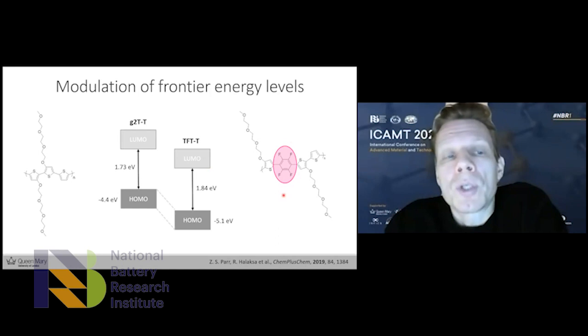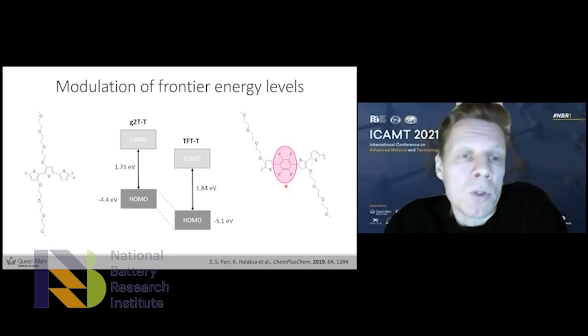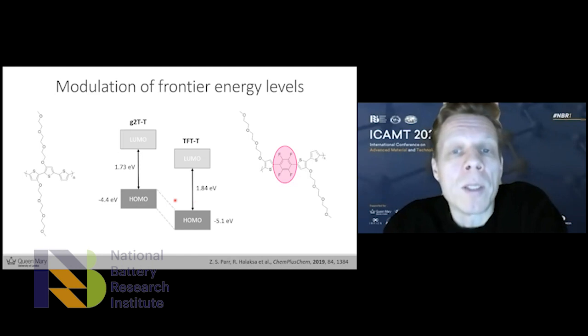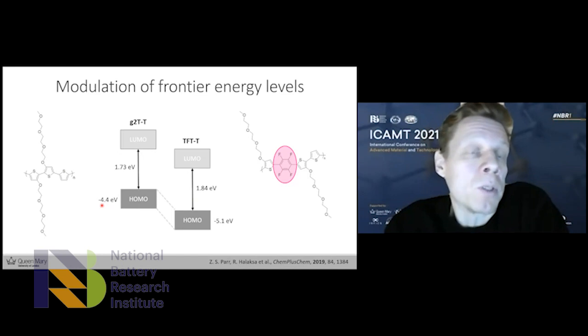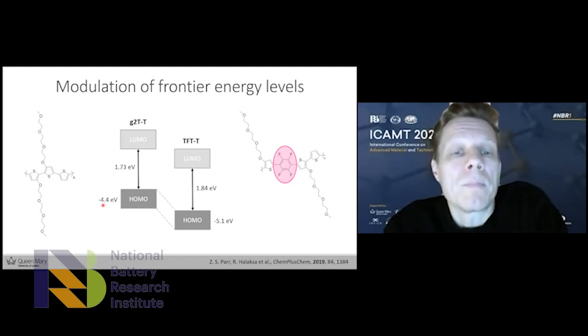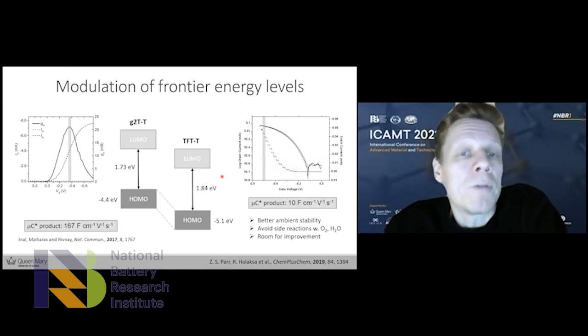What happens when we introduce, in addition to making a more green polymerization process, we also introduced this tetrafluorobenzene unit into the polymer chain. That's a very electron withdrawing and electron deficient unit. And that means that the frontier energy levels, the HOMO and the LUMO, they get much lower in energy compared to the benchmark material. So for example, the HOMO, which is important for charge injection into the material, reduces from minus 4.4 electron volts for the benchmark material down to minus 5.1 for this new material with the tetrafluorobenzene. That has significant effects on the operation of the OECT device.